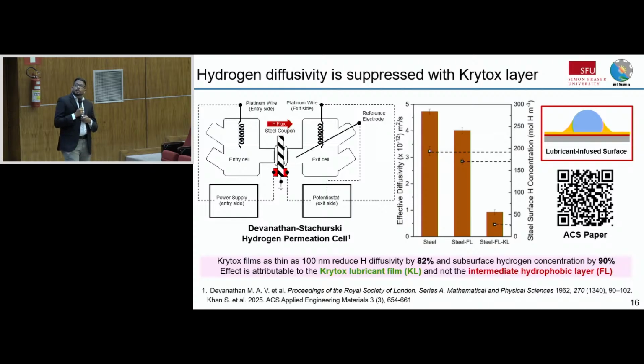And the important thing is that this is working not just by itself, but it's working along with this intermediate red hydrophobic layer. But just that red hydrophobic layer by itself is not enough to do the job. Adding that lubricant makes the job even better, right?